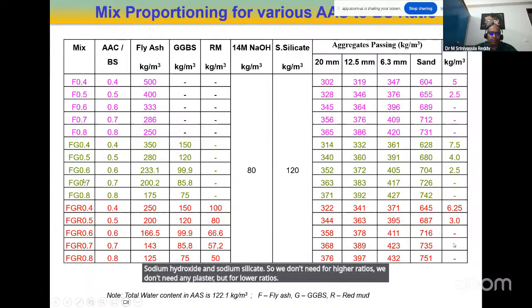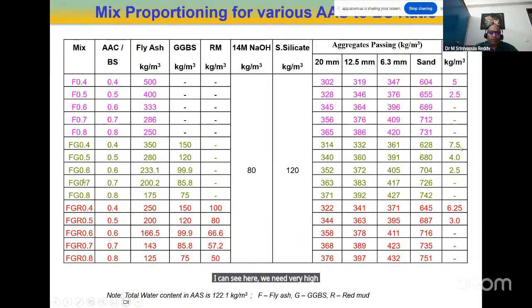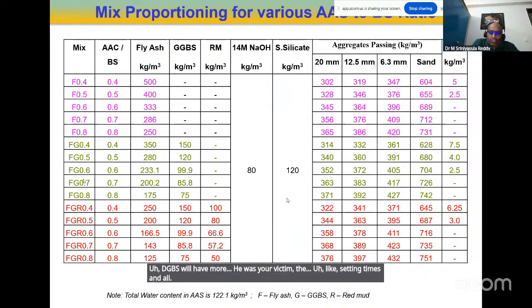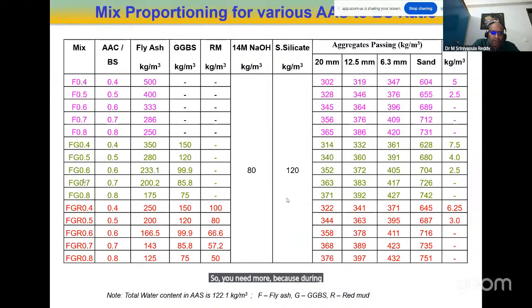this much. You can see here we need a very high amount of superplasticizer, because GGBS will have a huge effect on the setting times and all. So you need more, because even during setting time it will start reacting.